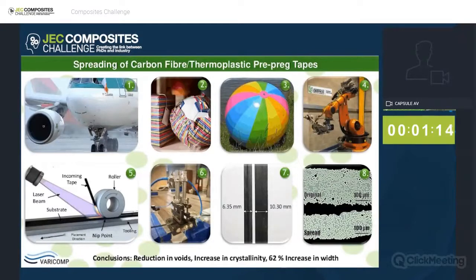As you can see in image 8, I have 2 optical micrographs, one of an original as received unspread tape and one of a spread tape with 62% increase in width. As you can see, there appears to be an improvement in fiber dispersion with less resin-rich areas. Also, we measured that there was a reduction in voids in the spread tape in comparison to the original tape.